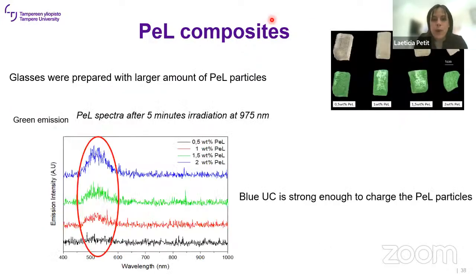And then we pump the glass at 980, to have this blue upconversion and then to charge the persistent luminescence. And here is the persistent luminescence of the glasses when we pump for 5 minutes with 980, and then we have this persistent luminescence. And we could confirm that the blue upconversion is strong enough to charge the persistent luminescent particles.